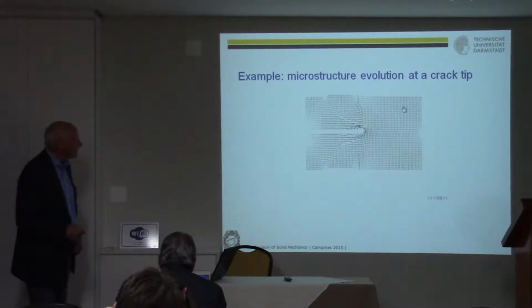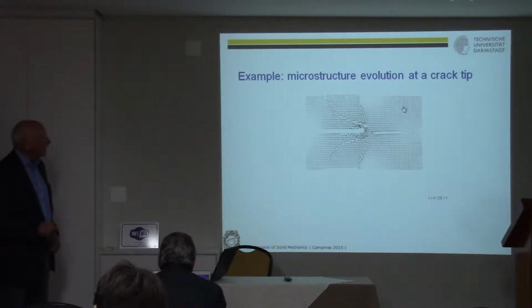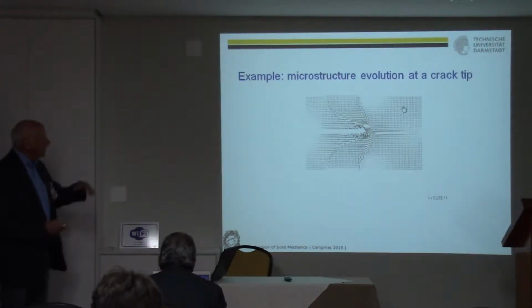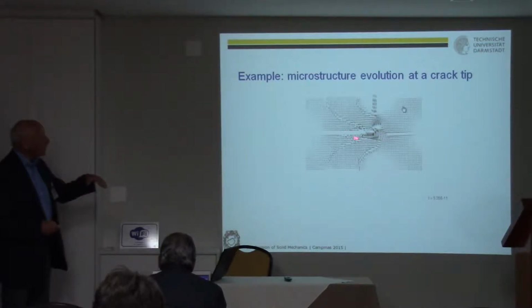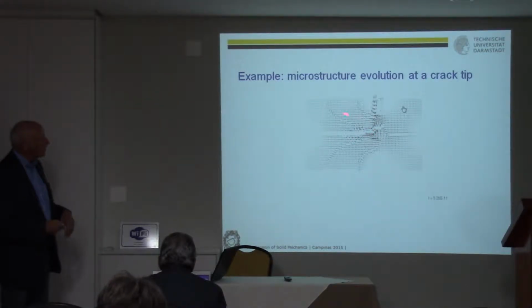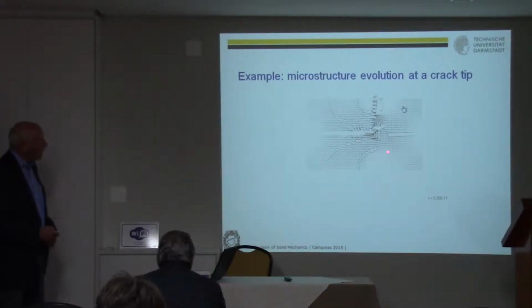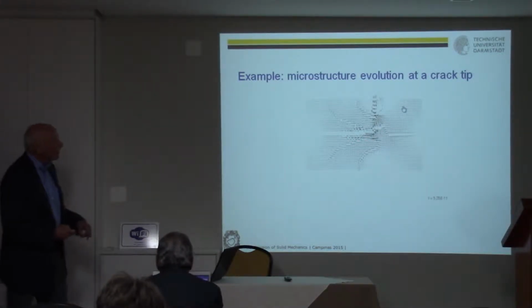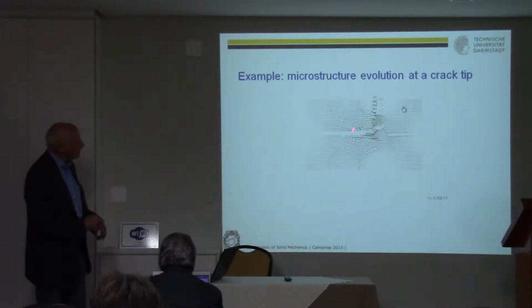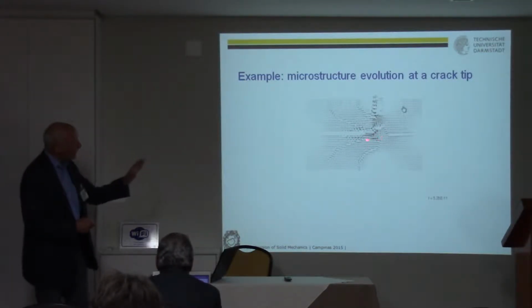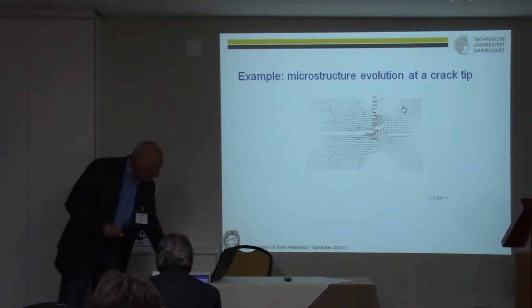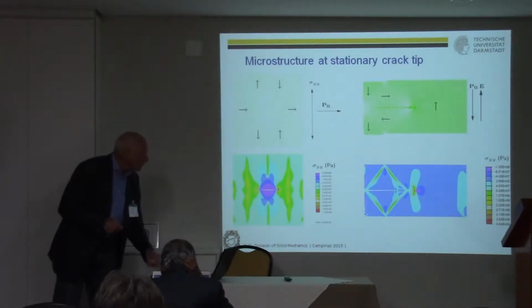Okay, here is one example, say the evolution of a crack in a loaded system where the crack then propagates, and here are the formed domain walls, and this, of course, is some sort of mess. You have to look a little bit closer, and then you see what happens in this crack tip region. This is only an example.